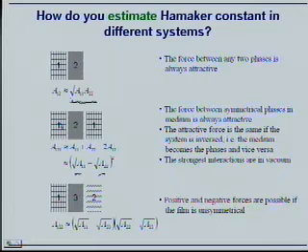From a colloidal viewpoint, any particles, if they are of the same material, would like to get together, in any environment, in any media. You can't adjust the media to make the interactions between the particles repulsive by van der Waals interactions. And van der Waals interactions are always present, so anytime you have particles, there is no chance of making them repulsive. The only chance that you have is to adjust the constant of the media to be the same as the particles, in which case they are not going to attract each other.